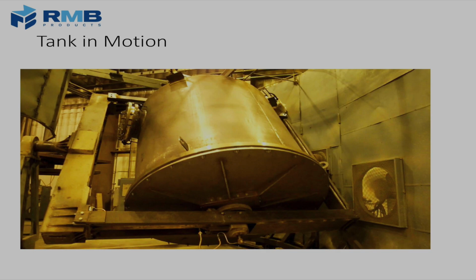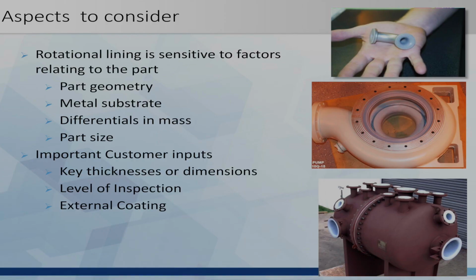It begins to rotate and gets right back into the oven for its heat process. So following the heat process is a very controlled cooling cycle. The cooling cycle is the most important part because we have to make sure that no stresses are imparted into that thermoplastic liner. So it's a very gradual cooling process to make sure it's not going to crack or contract very quickly. So there are many aspects to consider on whether or not something's a candidate for rotational lining.